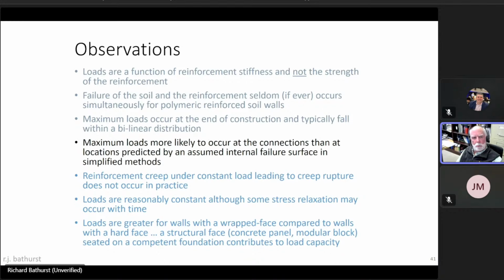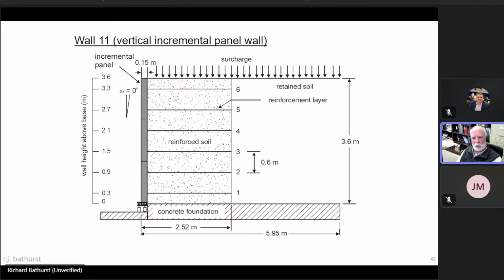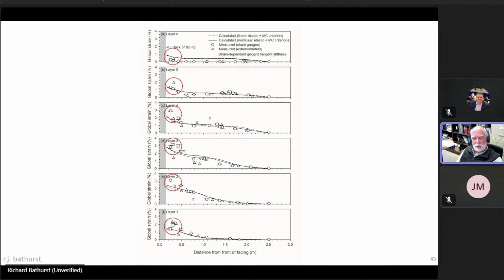And it's most easily demonstrated by looking at the results from our wall tests, including this incremental concrete faced wall. So this is a relatively rigid vertical structure. That is the facing. And if we focus our attention on the connections, or the strains in the vicinity of the connections, we get plots like this. Each one of these subplots is one of the layers in this wall, and the symbols are the actual measurements. If you focus on the symbols, you can see what I mean. Generally the highest ones are close to the back of the wall.